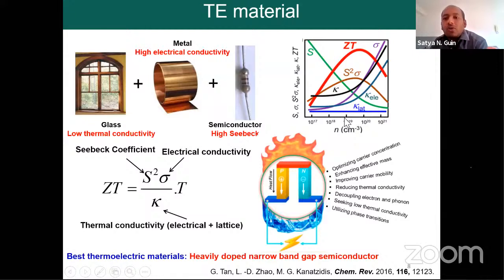Then you have to see the carrier concentration in this system. If the carrier concentration is low, you have to dope the system to improve it, so that you can get a decent amount of electrical conductivity without losing the Seebeck coefficient. And then you have to get a reasonably low thermal conductivity. This is another challenge, because if you increase the electrical conductivity, at the same time you increase the electronic thermal conductivity, because the charge carriers can also carry heat in the system. So the electrical conductivity should not be very low, and at the same time the thermal conductivity should not be very high. That's a challenge, and you have to play with that.